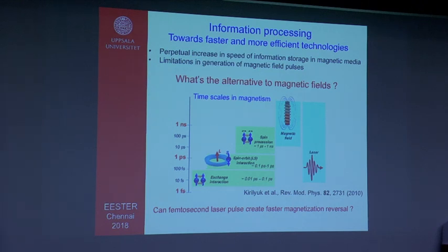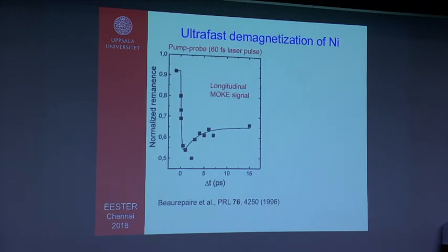This is a very recent development in the field of magnetism. I would say recent because the first successful demonstration came in 1996 by this group in PRL. They showed that you can really demagnetize FCC nickel, this FCC nickel film, with a 60 femtosecond laser pulse, in a time scale you can see is of the order of picoseconds. This is the so-called pump probe experiment. If you measure the longitudinal magneto-optical Kerr effect, you can look into the remanence here. The demagnetization happens in a few picosecond time scale. That means very fast with a laser pulse.